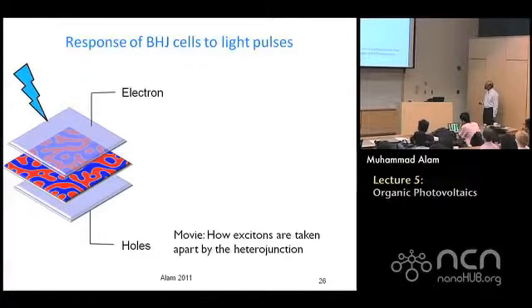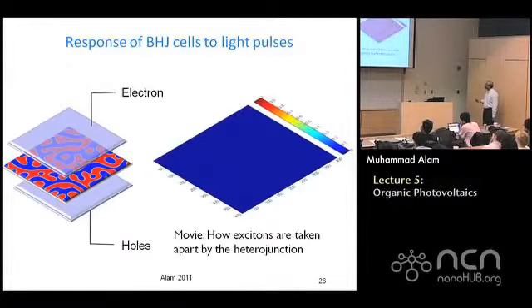But this is a movie that shows how the excitons are generated in the complex structure and how they get gradually phase segregated. They get dissociated at the contacts. So let me show you one more time. What is happening is that a light pulse came in, and it generated excitons in one of the phases, like raindrops. It is coming and getting collected on the red phase, and then they are finding the junctions and getting dissociated. Since I had one pulse, they will either self-recombine or get dissociated at the junctions, and that is how this pulse comes in.